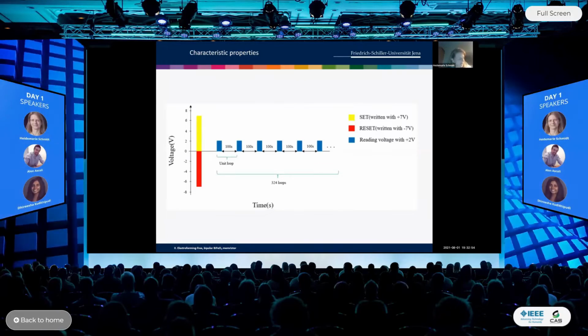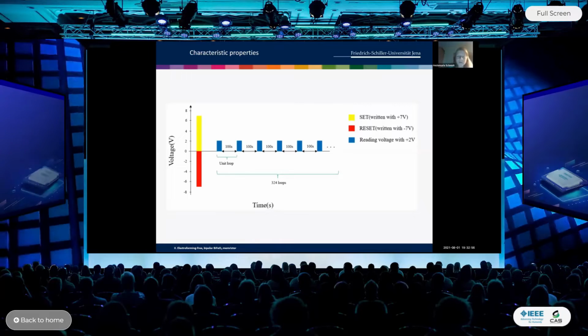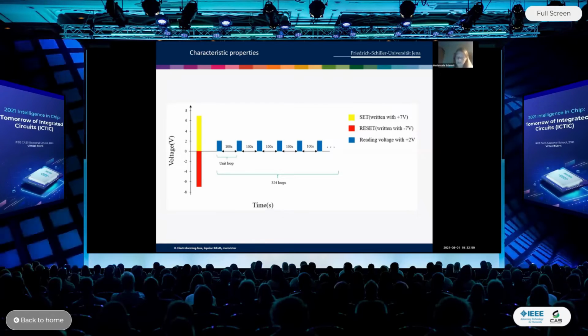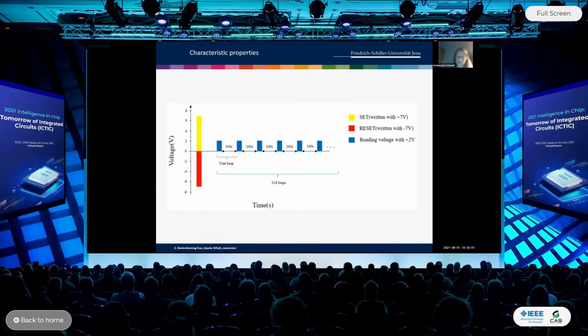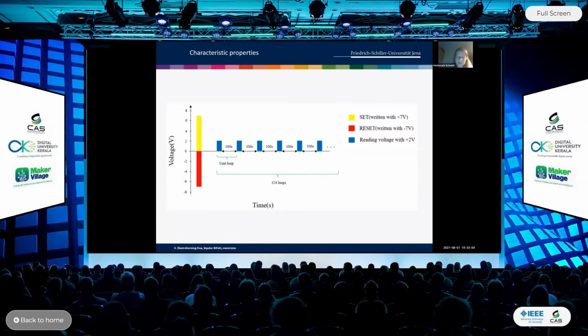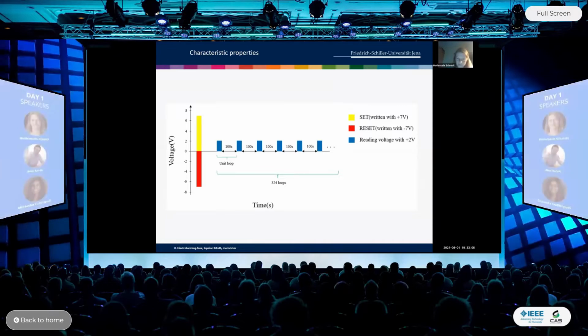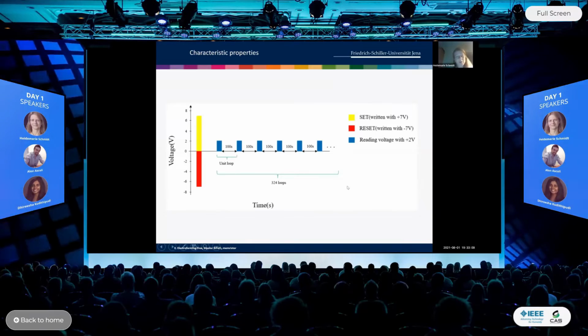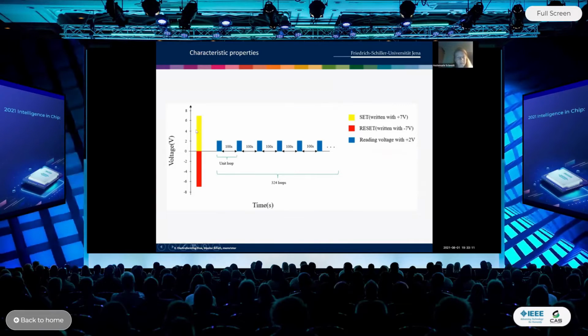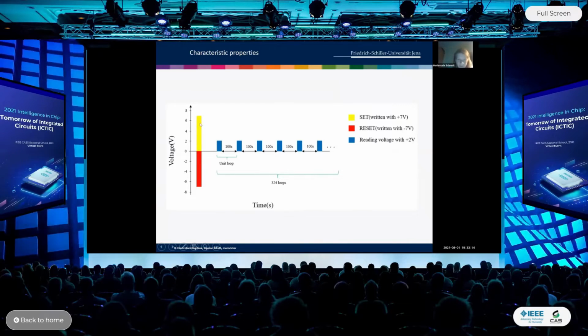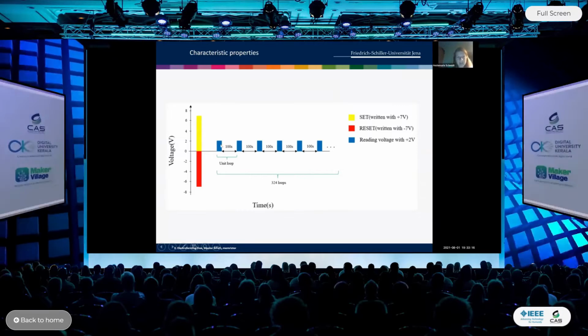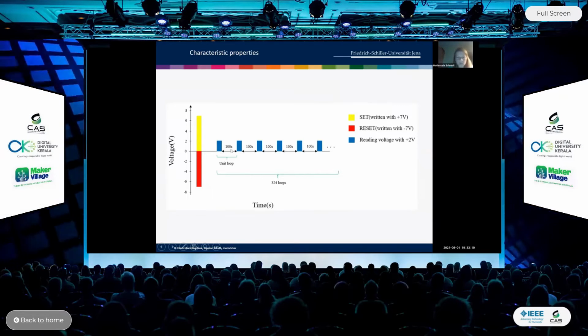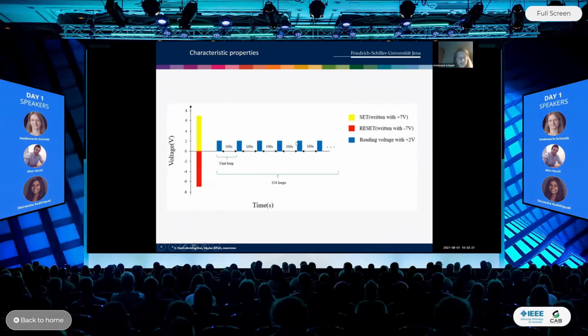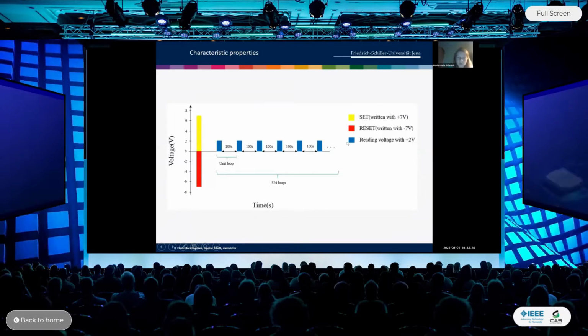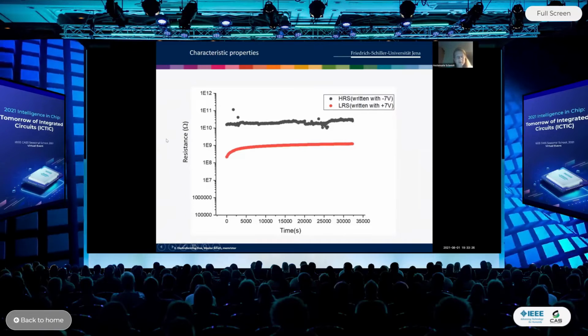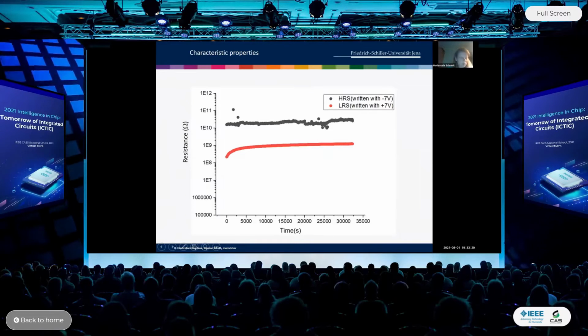But before I do that, because it's a tutorial, I will also give some explanation of how this memristor is further characterized. The first thing is, how long can this new resistance state be reconfigured in this memristor? In order to analyze that, one defines, for example, the low resistance state or the high resistance state, and then one continuously reads out the resistance state of this memristor with a readout bias. So this is shown here. This is called retention of such a memristor.